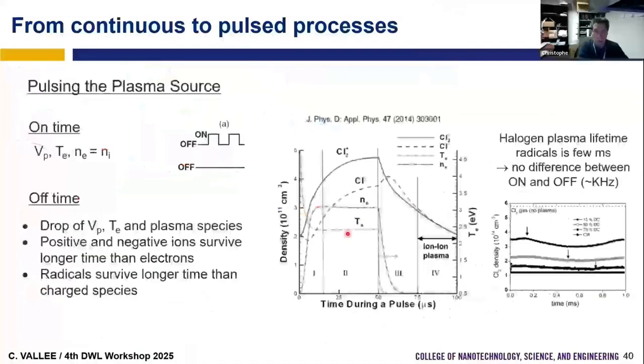energy of ions. So in fact, what we know right now is that if we pulse, all the species in the plasma don't have the same decay. So they survive more or less longer in the off state. For example, electrons: when you stop to apply the power to your plasma, you will lose your electrons very fast. Then the decay of ions takes more time. And radicals usually survive a very long time.